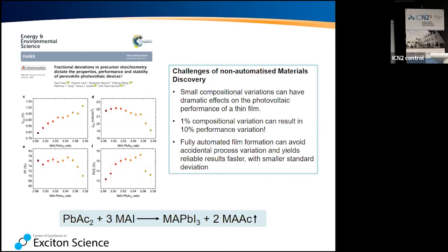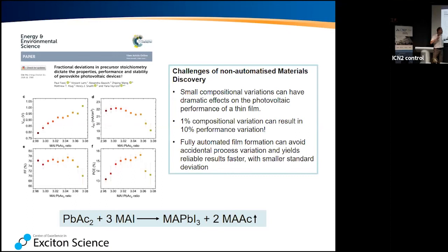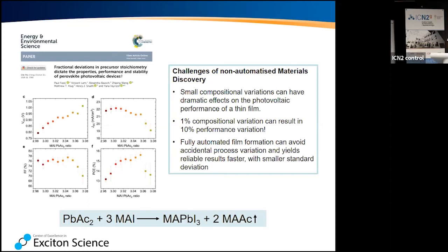And what Henry and his group and their collaborators showed here is, let's move on to the power conversion efficiency. You see here, stoichiometric is 3:1. So here's your 3:1. And now you're slightly changing. So this is actually 3.03. So it's 1% off. So you change your ratio by 1% and you moved from a solar cell that has less than 14% to something that has above 15%. Simply by changing your ratio by 1%. And this is also something where we think that if you have a system that very, very accurately monitors what your ratio is, it'll be much easier for you to do the optimization of your solar cells.